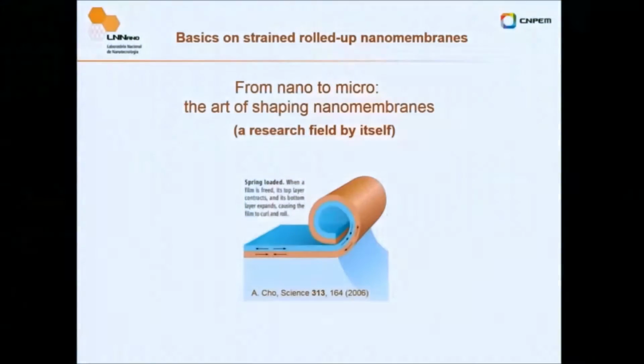One of the main features is to combine layers, which can be of the same material or different materials, with different stress configuration. You can have one layer with a compressive stress combined with one layer of tensile stress. And once you remove it from the surface, the material tries to roll, depending on the intensity of this internal force. You can also wrinkle, delaminate or crack. That is the simplest manifestation of this phenomenon when the stress is too high.